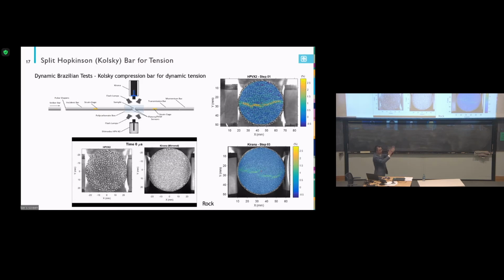Then we use two high-speed cameras to look at both sides simultaneously, and then we apply different patterns for the DIC, digital image correlation, to understand the full field displacement or strain. So here is the video. When it's compressed, you can see it generate tensile stress in the center, and you will see the crack in the center like this. So the sample just splits in two parts, so some people also call it the dynamic split test. Then with digital image correlation, we see what the strain is when the specimen cracked. So we use the compression bar for the dynamic tensile test.